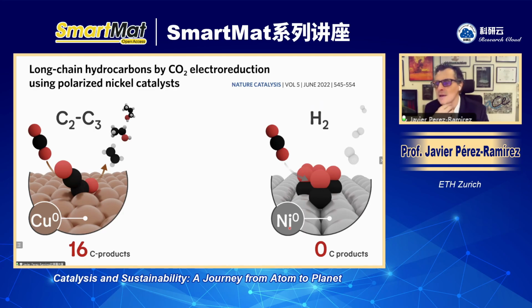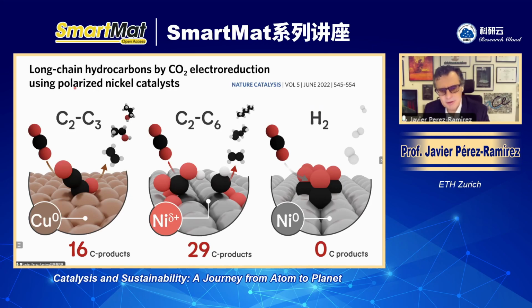It will mostly reduce water into hydrogen due to a very strong adsorption of carbon monoxide on the surface of metallic nickel. Instead, we have been working with polarized nickel catalyst, which is trying to incorporate oxygen on the surface of the catalyst in a stable manner. And we have achieved that by using, for example, nickel phosphate as precursor of the catalyst for converting